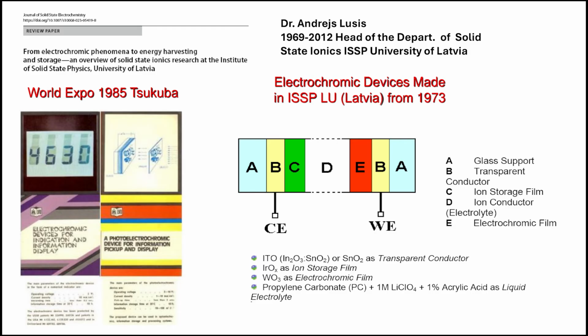Another is the ion storage film, which is usually nickel oxide now, but in this period was iridium oxide. The electrolyte between these two materials was usually protonic or lithium electrolyte. We also demonstrated this device at the Expo in Tsukuba in 1985. So it was an extremely large accumulation of knowledge.